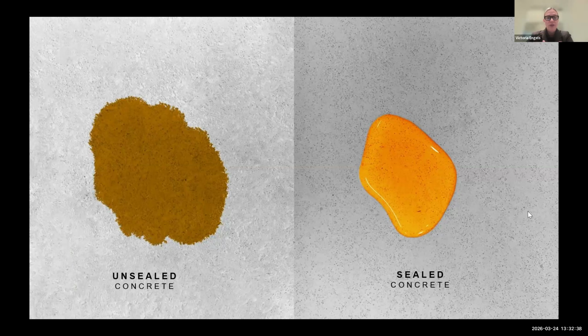So what do fabricators use to seal concrete? There's essentially two types of sealers: reactive sealers and coating sealers. Reactive sealers are thin fluids that literally soak into the concrete and chemically react with the ingredients. This provides invisible protection without changing the surface appearance. In contrast, coatings are thicker fluids that are rubbed or rolled onto the concrete surface, and which, once cured, form a hard protective surface.